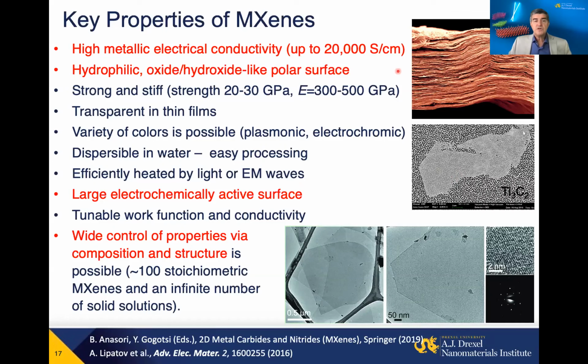But as I mentioned, one of the key properties is high metallic electrical conductivity. This is where this material is largely also added to the array of existing materials. And you can see, for example, here, MXene is assembled in a film, several micron thickness. So there are a couple of thousand of flakes in cross-section here.